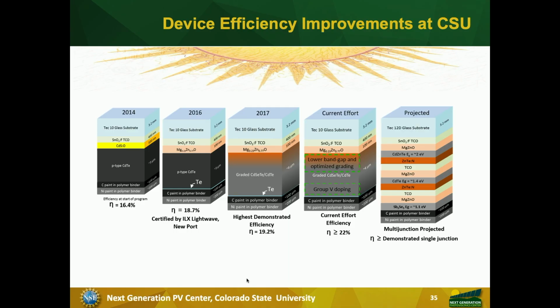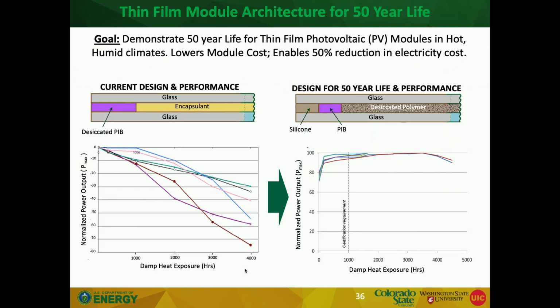Our ultimate vision is to make a multi-junction where we run at this speed and make 35-40%, which will be electricity at 1 cent a kilowatt hour or free, essentially, in some sense, which will be a bad way to think about in business. Now, one of the other ideas that we developed in the commercialization of cadmium telluride is doing the encapsulation slightly differently. The current encapsulation involves a desiccated PIB and encapsulant. We have replaced that with a much better structure, which there is a booth outside, and it also does better in terms of damp heat.